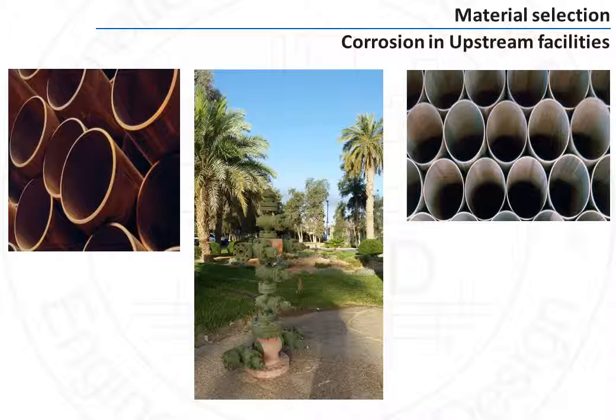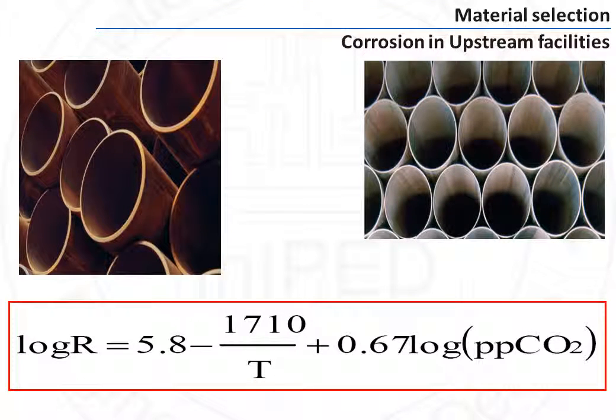This phenomenon is described by a corrosion rate formula. Such a formula gives the corrosion rate in millimeters per year as a function of the temperature and the content of CO2 — the partial pressure of CO2 — which is the concentration of CO2 times the pressure in the line. Such formulas come from various publications, in particular research publications, and many are synthesized in API 581. As you can see, the corrosion rate differs for every difference in temperature and every difference in concentration of CO2, so this calculation has to be done for every line of the plant.